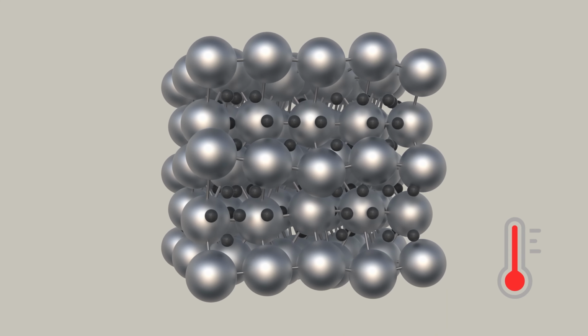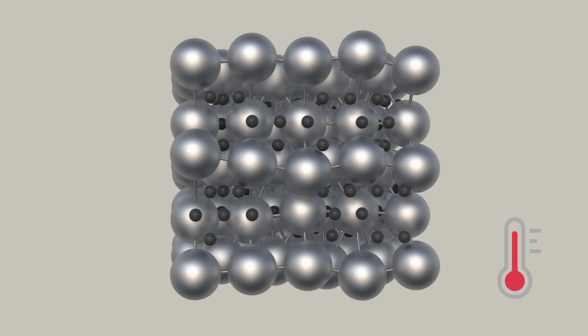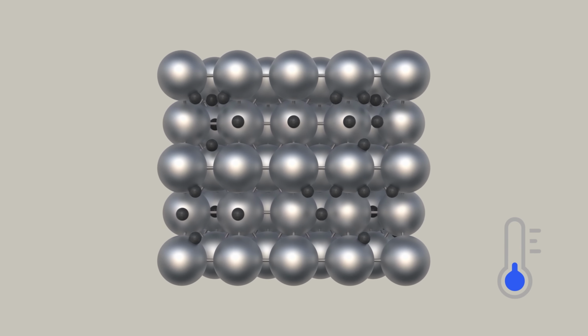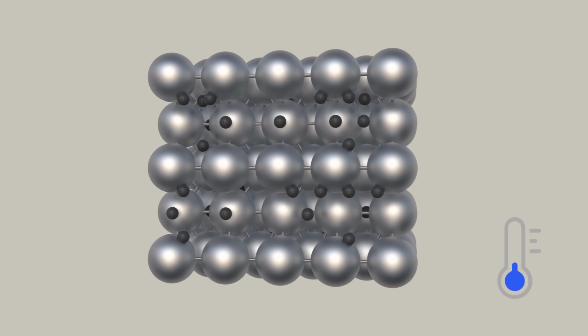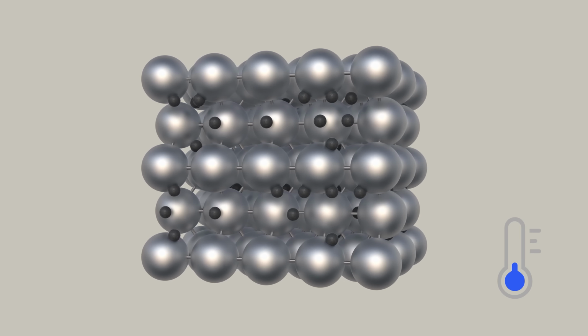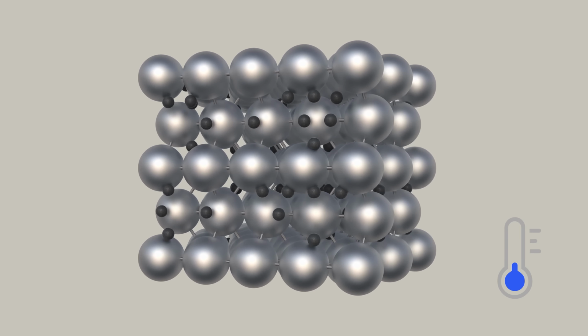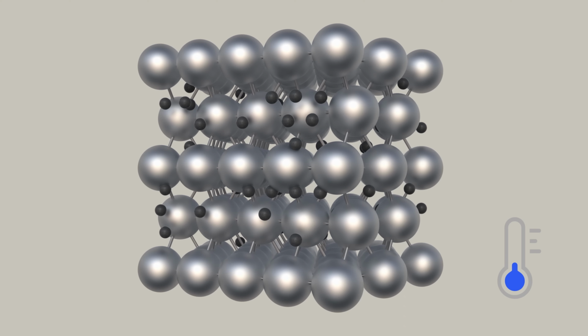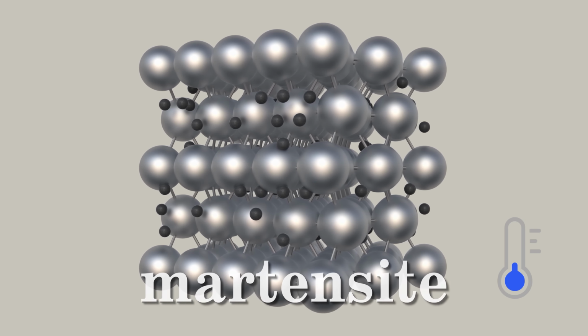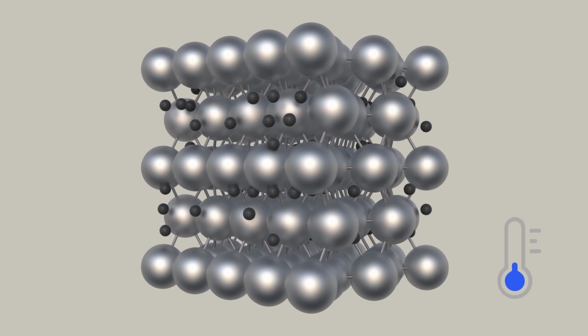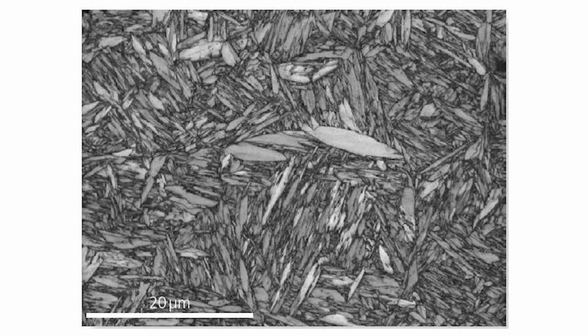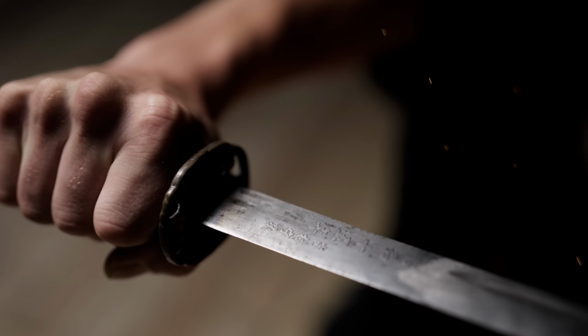In contrast, the very thin layer of clay on the blade means that it cools very rapidly, so more of the carbon is trapped in the lattice. This forces the lattice structure to change from cubic to tetragonal, making a form of steel known as martensite. Since the trapped carbon puts stress on the lattice, martensite is incredibly hard, exactly what you'd want for the edge of a sword.